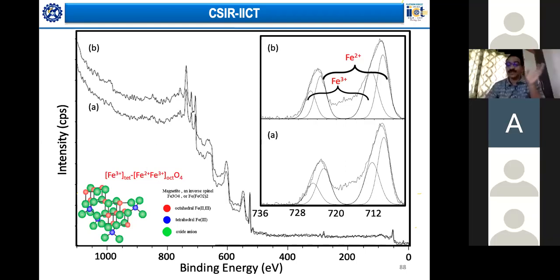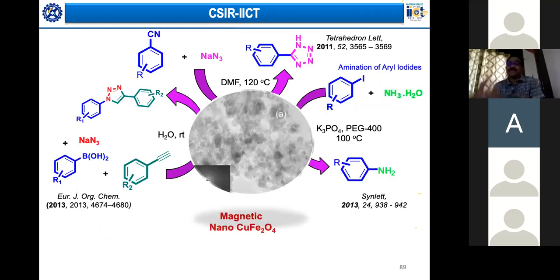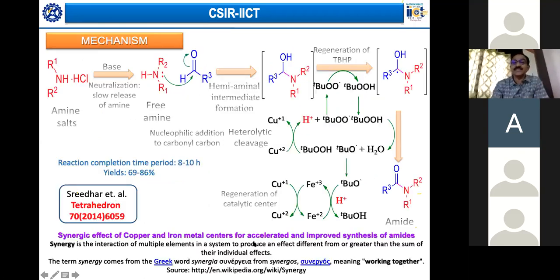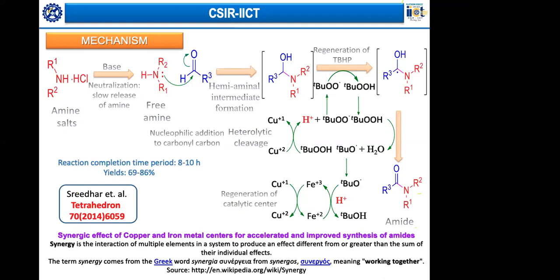Then we did a little more, changed to copper as a dopant, giving copper Fe2O4. When we use such reactions, our interest is to understand the mechanism, because if there is no synergy between the various ions present in these materials, the reaction yields, selectivities or conversions would be less. But when we did this reaction, you can see that there is a synergetic effect between the copper and iron metal centers in this material. That is the reason we are seeing an increase in yield, and this reaction was getting completed in about 8 to 10 hours with higher yields.